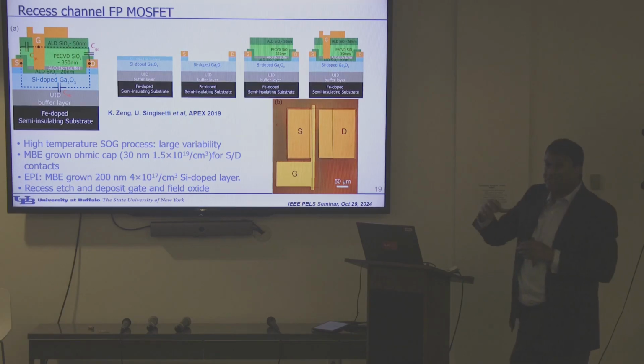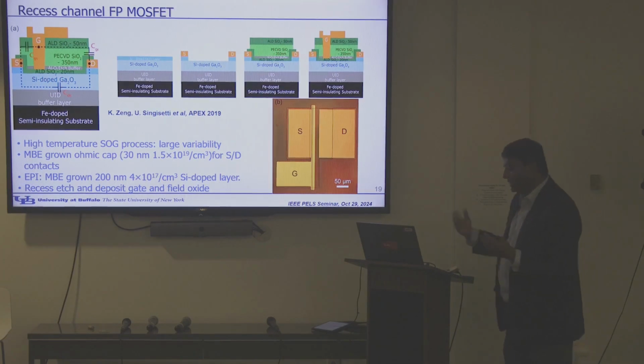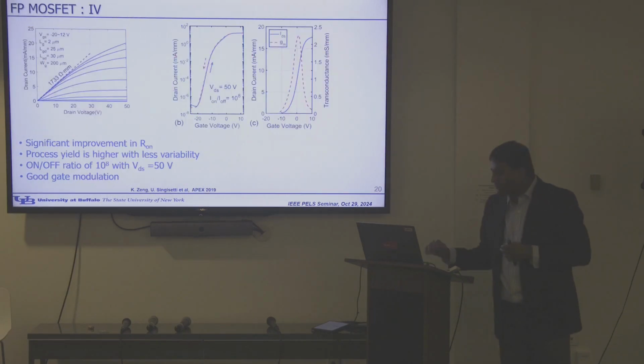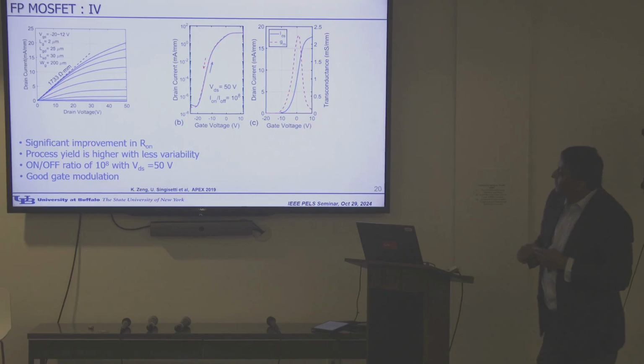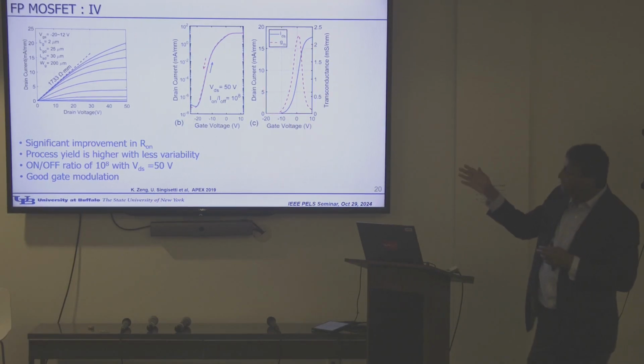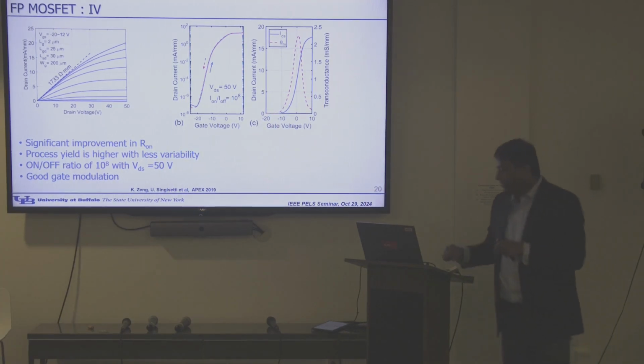And I just want to say that ion implantation also works pretty good. People have shown ion implantation to make N plus layers. That also works pretty well in gallium oxide. It's very stable, so you can anneal at high temperatures. So you can see again on the left here, the on resistance is improved. On the middle curve, on-off ratio again very good. Good depletion mode device, and we use small pieces but very well behaved. Good uniformity across the whole wafer.